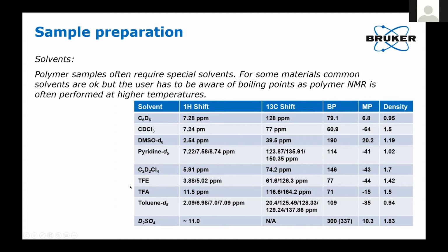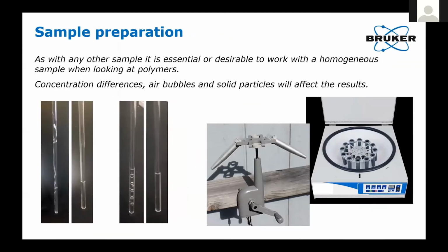And the scary solvent is deuterated sulfuric acid, which once I heard of a case where a 10 millimeter tube of sulfuric acid at about 130 degrees cracked in the probe. Gives an interesting result. As I mentioned, sample preparation can be tricky.